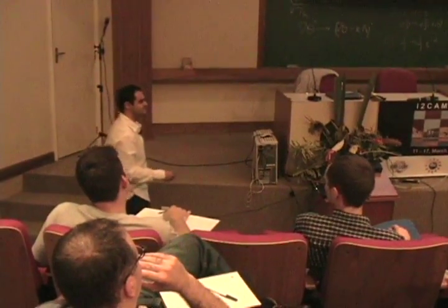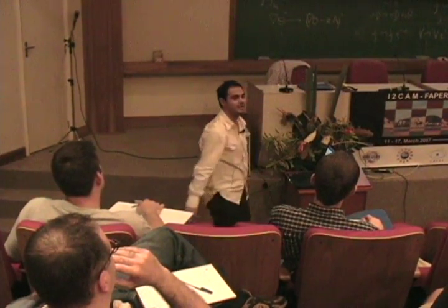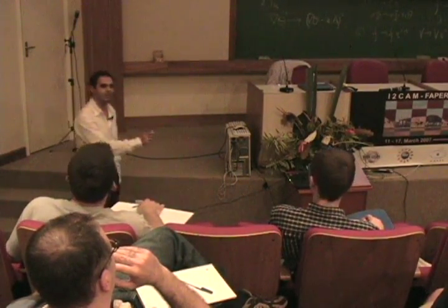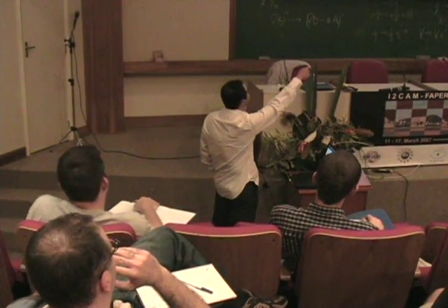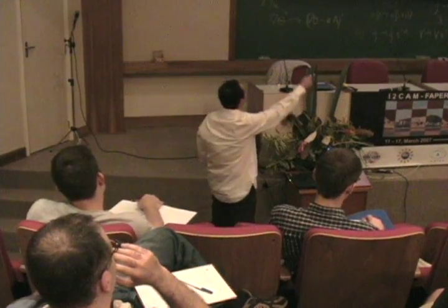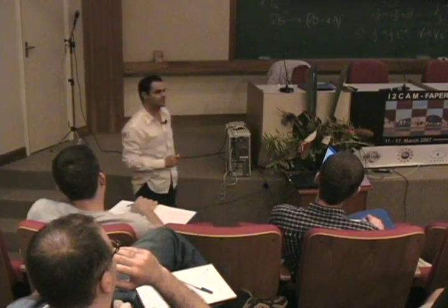So that's the phase diagram for the 218s, for that bilayer version. You see the rhodium material is an antiferromagnet. It has a T_N of 2.8, which is smaller than the 115. When you replace rhodium by iridium, that's the out-of-plane substitution, if you remember, you suppress the antiferromagnetism, but you go to a spin glass state at the iridium side. It's not a superconductor, right?